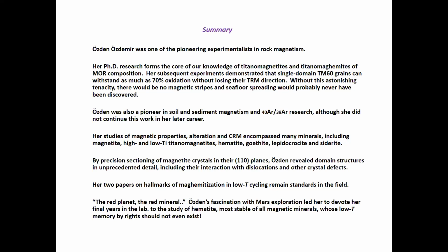So to sum up, Özden was one of the pioneering experimentalists in rock magnetism. Her PhD research still forms the core of our knowledge about titanomagnetites and titanomaghemites of mid-ocean ridge composition. And she did look at other compositions, but this was the focus of her work. And maybe the most important experiments were those early ones at Toronto, where she showed that single domain TM60 grains, that's what you find at mid-ocean ridges, can withstand as much as 70% oxidation without losing their TRM direction. Without that astonishing tenacity, there would be no magnetic stripes. If we didn't have the magnetic stripes, would we even know about seafloor spreading and plate tectonics? We would not be in the era that we are.